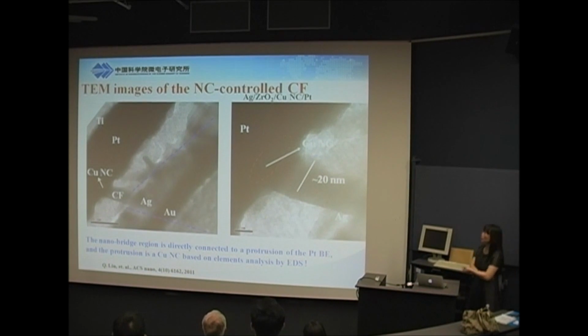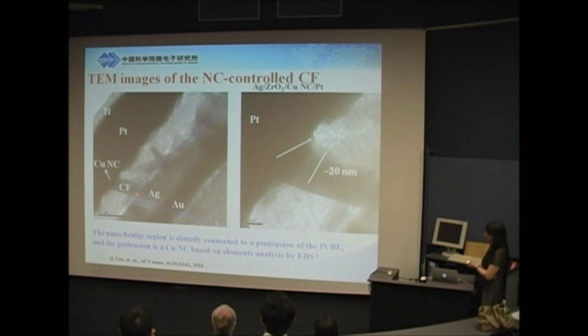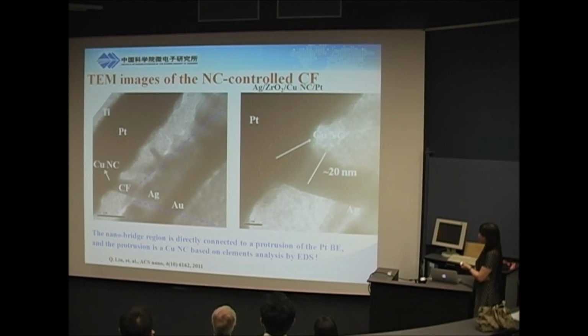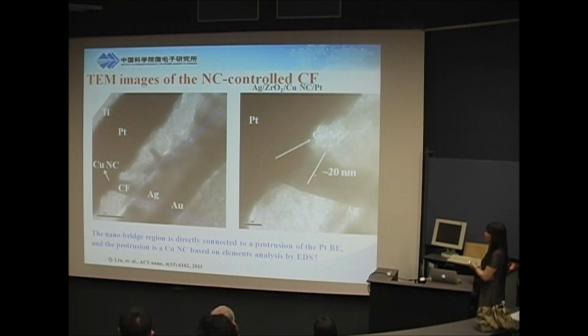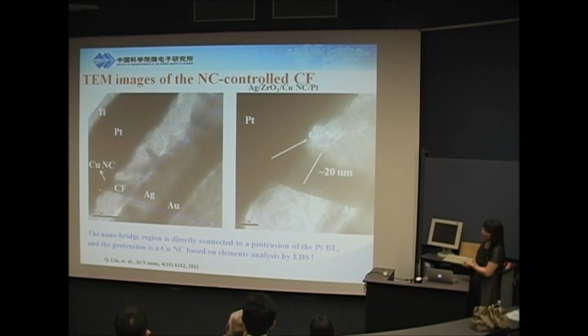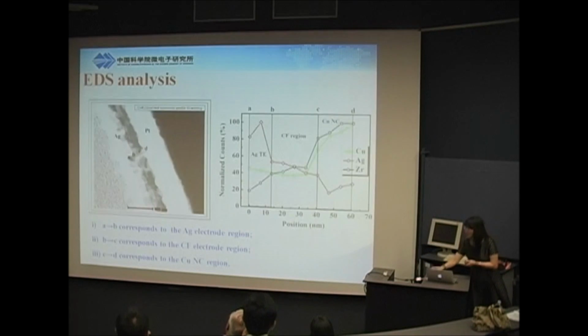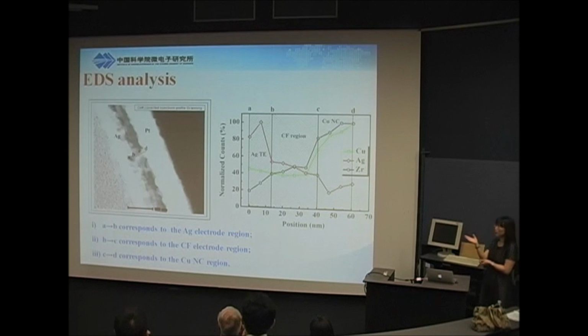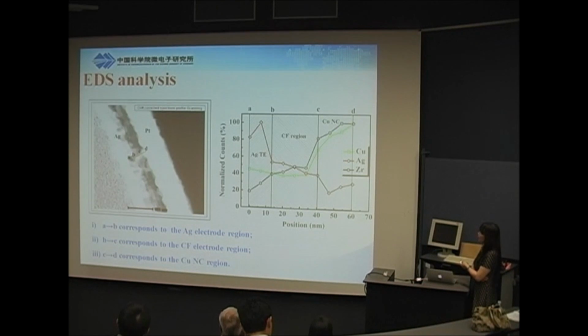Next, we still use TEM to observe. We can see this is a nanocrystal. The filament was formed along this nanocrystal. This is an enlargement of this area. So this proves that the filament can really be controlled to grow around this nanocrystal. To further confirm what this filament consists of, we can do some mapping. Here is a filament. We can analyze the elements in different areas.